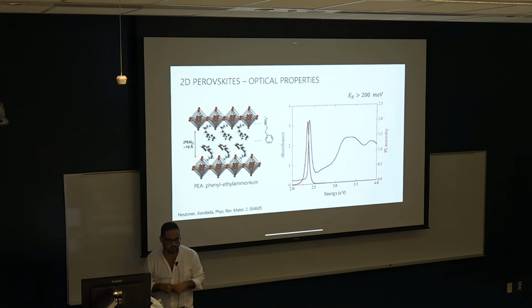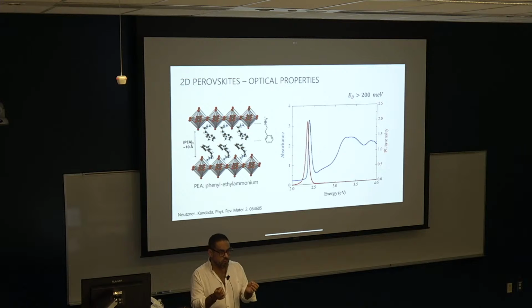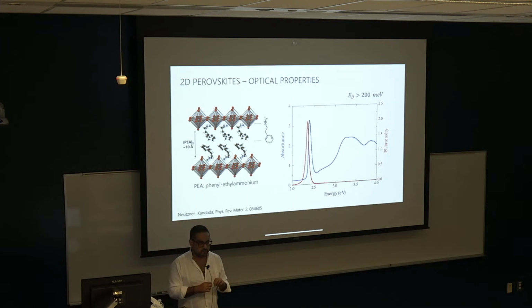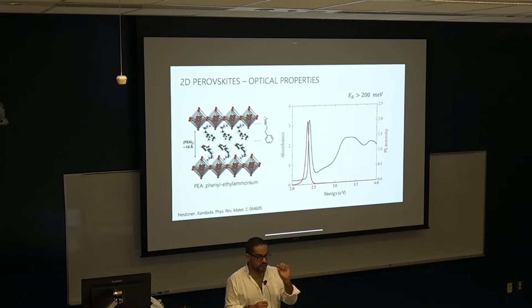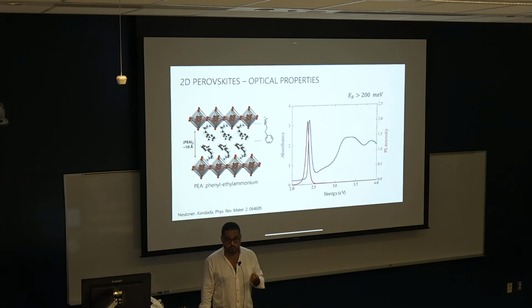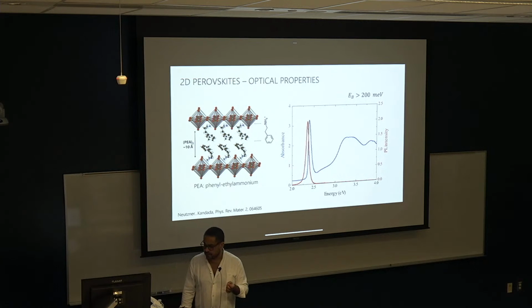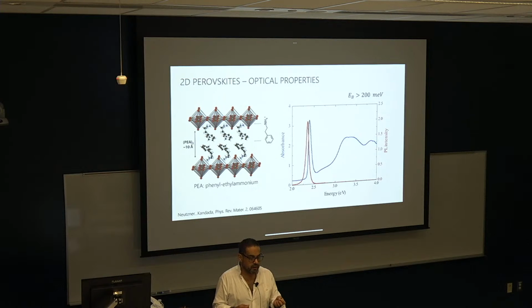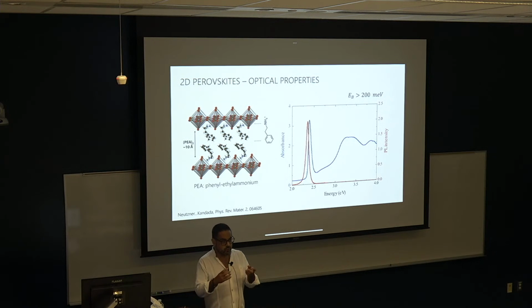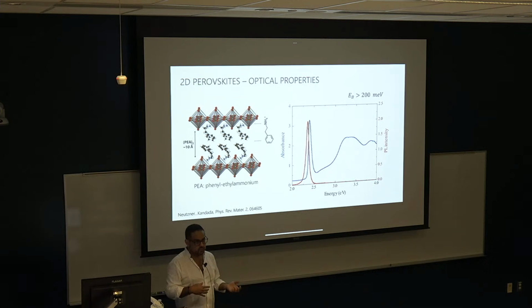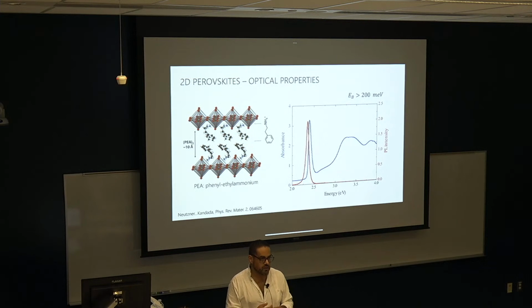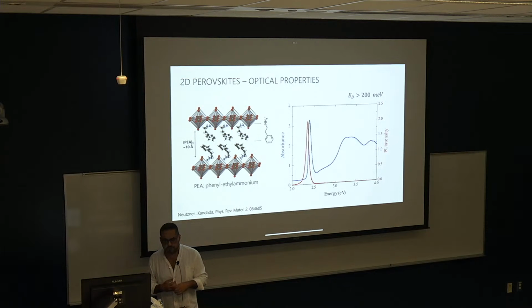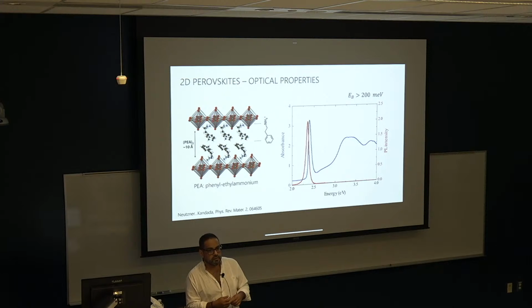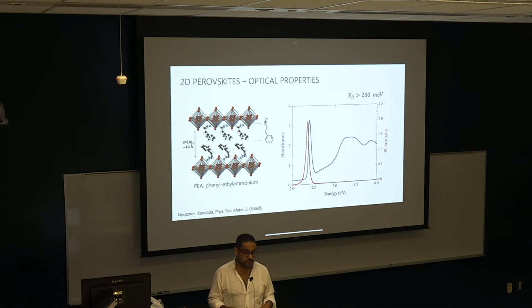It looks like a multiple quantum well, like a very, very thin multiple quantum well in composite semiconductors like gallium arsenide. But there's something very different about those materials. One is the layers are very thin, these single octahedral layers, so you get very strong quantum confinement effects. And there's also a very high contrast of the dielectric environment between the lead iodide layer and what's in between, essentially vacuum with these organic cations in very low density, essentially 1 per unit cell. And so you end up with very strong dielectric confinement as well. So that's a very important concept. It has very important consequences in the optical properties.